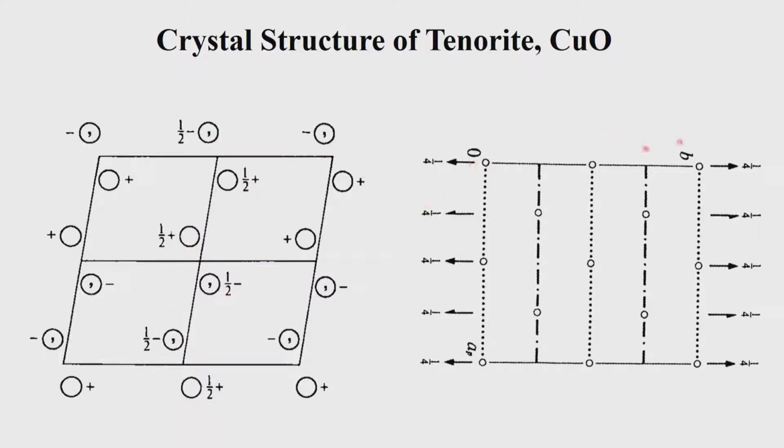We see here in this diagram, if we now carefully look at this particular diagram, we get a C glide which is associated with the origin over here. And then we also get a twofold associated with that origin. So, there is a C glide and a twofold intersecting with respect to each other with 2/m symmetry. So, it is a centrosymmetric monoclinic system. Apart from that, we also have the fact that these 2 and C are intersecting at this origin. So, it has to be this space group C2/c. So, we have inferred that the copper oxide tenorite goes into the space group C2/c.